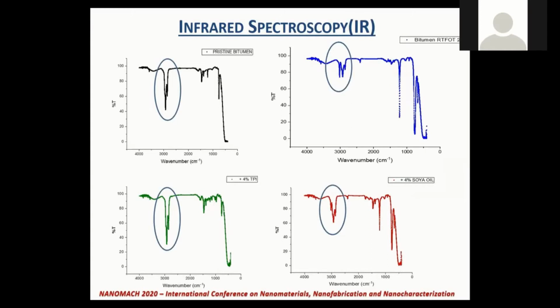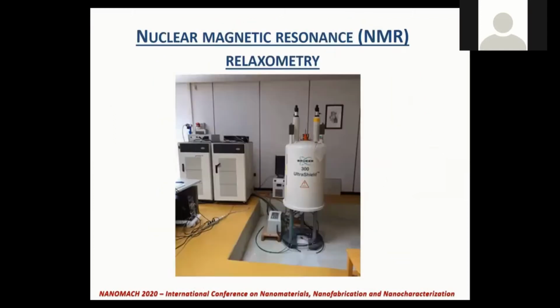The opposite behavior is observed for the typical peak of the sulfoxide functional group, where we have higher intensity peaks for the aged and the aged plus oil, and medium small peaks for the non-aged and aged bitumens added with TPI. This confirms once again that the additive chemically reacts with the bitumen, regenerating the oxidized molecules.